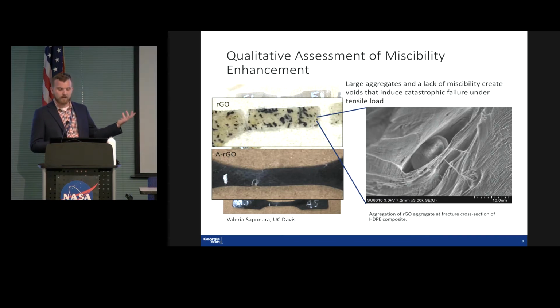To follow this up, we can look at this, and we see that these aggregates at this interface, this is presumably a graphene oxide aggregate, not only do they aggregate and they're not mixing with the polyethylene, that's a problem, but they also form these voids within the polymer matrix. And this is well known in composite literature. If you look at a variety of different metal oxide type composites, they exhibit a similar failure mechanism.